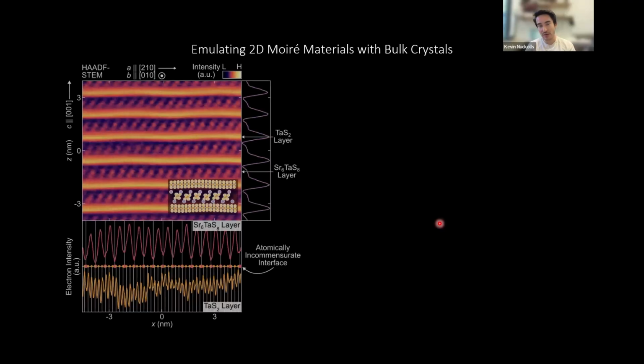It's nice to see it in diffraction, but I also like seeing it in real space. And so collaborating very closely with David Bell's group at Harvard, we did cross-sectional TEM images of these types of compounds. So this is a different batch. It's not the same batch as the previous slide, but it has the same lattice motif. And we're now cutting through all the layers and imaging the cross-sectional image of the layers. And you can see indeed the structure of this foliated superlattice. So it's the natural intergrowth of different monolayers in this bulk crystal.